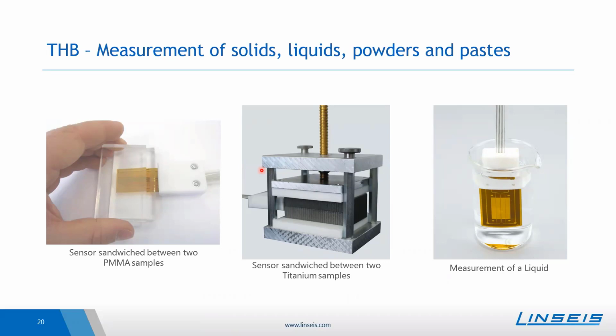Also for liquids, powders, and pastes, this sample preparation is very easy. Typically, it is enough to just use a beaker, fill it up with the liquid or powder, and hang in the sensor with the metal frame here, which is not visible within the water. Here is also the metal frame tip. The metal frame is necessary for the liquid, powders, and paste measurements because the sensor foil is very flexible, and with the metal frame, it is more stable. And within a liquid, it is then avoided that there is a bending and the heat generated by the sensor will be accumulated. So with the metal frame, it's very stable and because of that, then useful for the measurement of liquids.